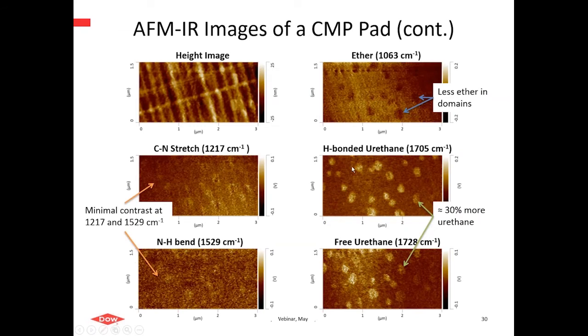We also can collect images and maps from some of the stronger absorbing locations in this material. For instance, if we go after things related to soft segment or ether linkages, we get an inverted map now of those harder urethane, hydrogen-bonded or free urethane locations in this morphology. And other strong absorbances are less well resolved in the mapping. One thing we clearly can identify, again looking at the relative intensity in these maps, is that we see urethane enrichment in these harder domains. Again, rounding out our understanding of both the chemistry and the mechanics, the morphology and the chemistry.